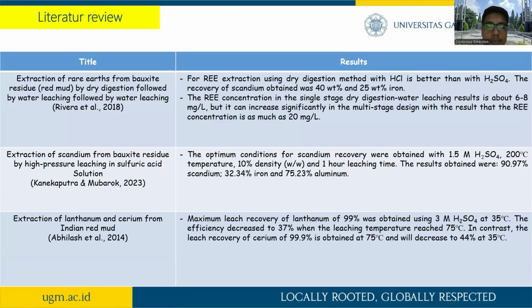This is a literature review from 3 journals I got. First, extraction of rare earth from bauxite residue by dry digestion followed by water leaching, by Rivera et al., 2018. The result for extraction using the dry digestion method with hydrochloric acid is better than sulfuric acid. The recovery of scandium obtained is 40 weight percent and 25 weight percent iron.